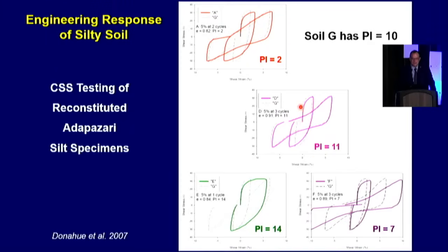You can see obviously a PI of 11 essentially is the same, but a PI of 2 and a PI of 7, very little difference. So when I look at liquefaction effects and those stress-strain curves, I think I should look at them all the same. A low plasticity silty clay acts much like a very low plasticity or a non-plastic clay. Once you get up to a higher PI, then it becomes very clay-like.